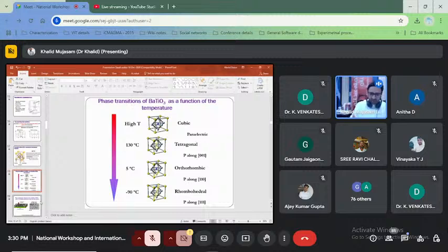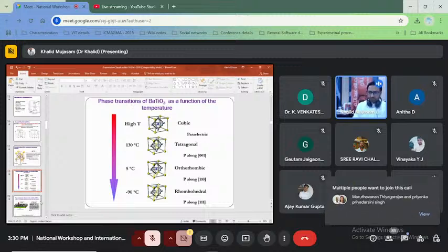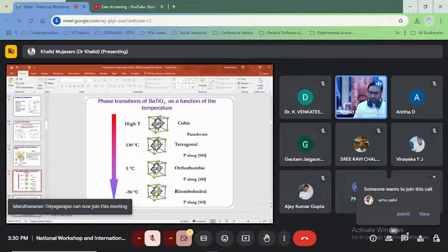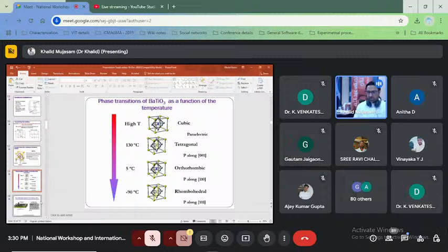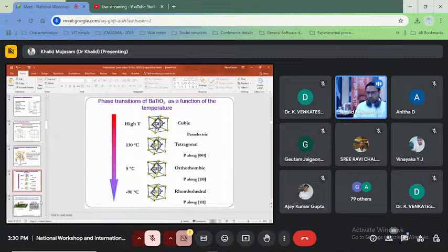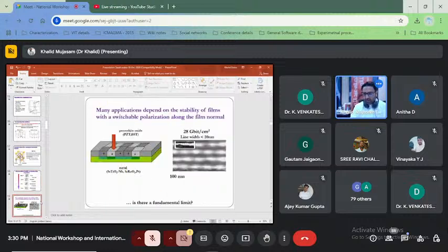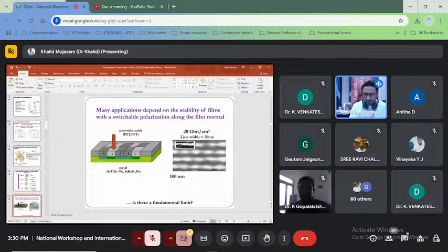So you can say there's a phase change happening in these materials, which is quite unique, changing the structure of the material, and the polarization is accordingly changing from the 001 plane to the 111 plane. So this is from barium titanate or strontium titanate doped with niobium and other materials. You have this 28 gigabit per centimeter square. This is the line width, in less than 20 nanometer, where you can see how much energy, how information can be stored actually.